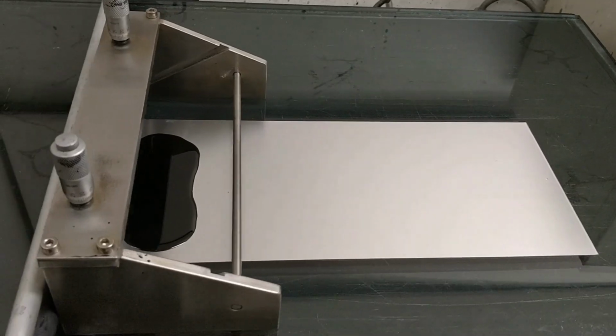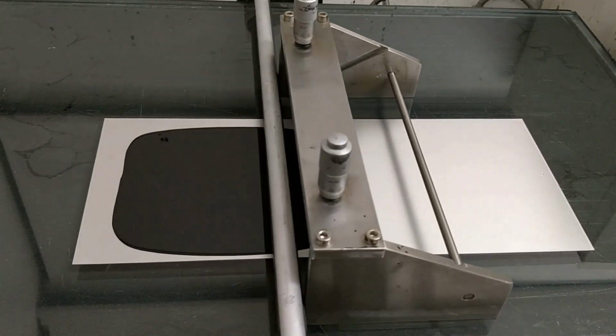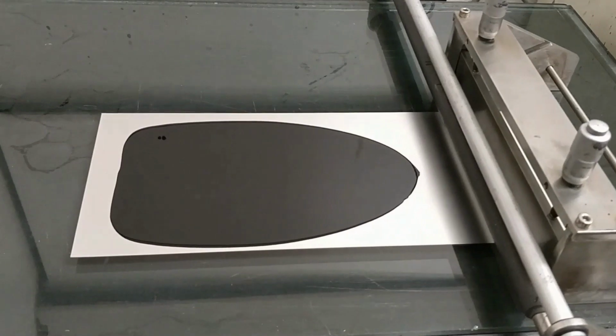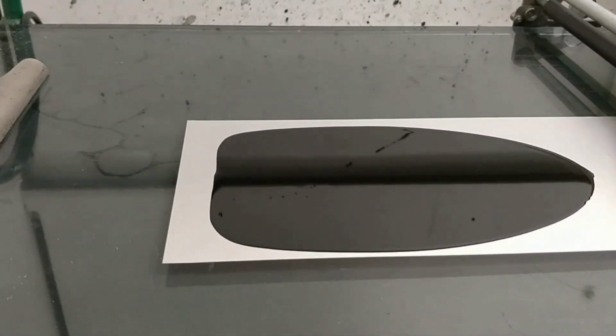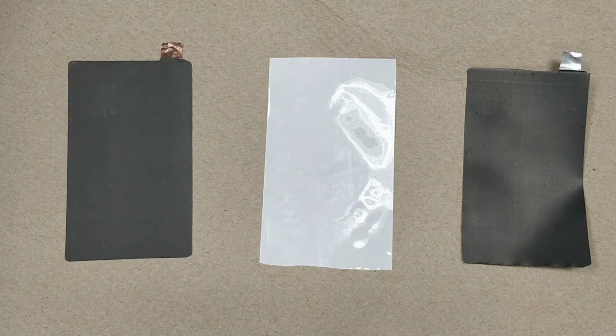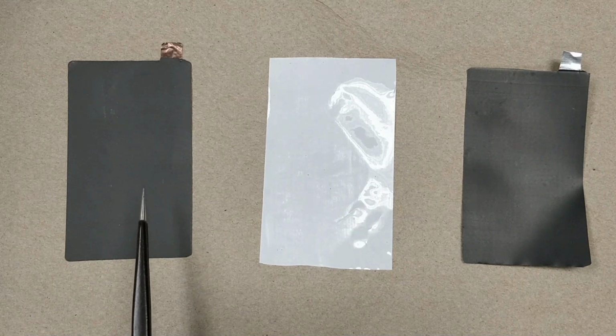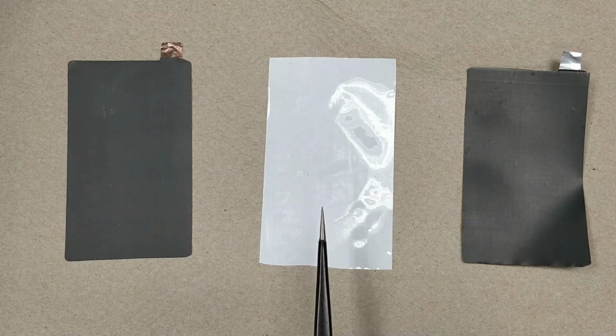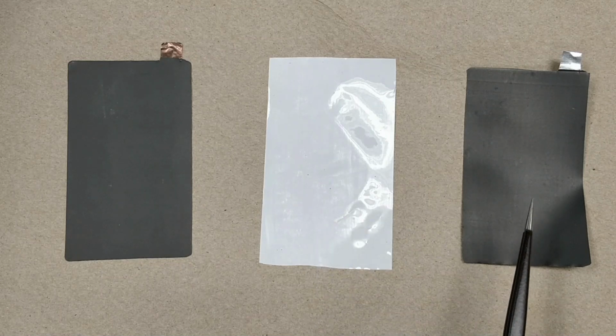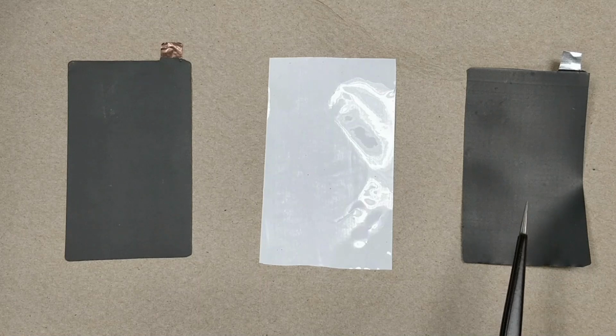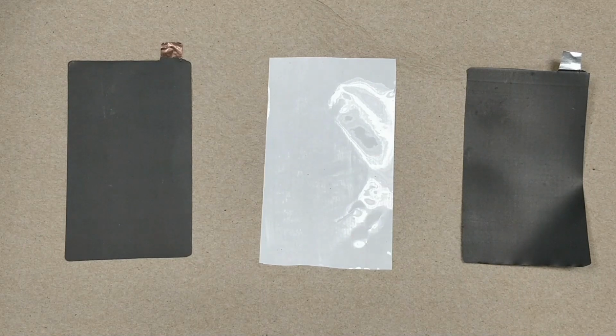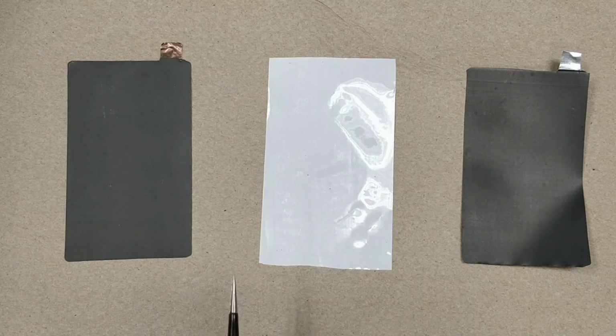The prepared cathode powder is then mixed with conductive carbon and a liquid paste and cast onto an aluminum current collector as a thin film. After the drying, the positive electrodes are punched from the aluminum foil. Similarly, graphite powder is cast onto copper foil and punched in a similar way to form the anode. The two electrodes are separated from each other using an insulator polymer sheet separator, which can soak in the electrolyte.